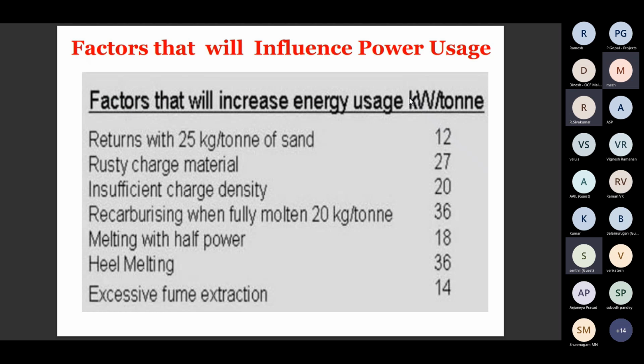So these are the various factors that will increase the energy usage in kilowatt hour per tonnage. These statistics are average statistics. Returns with 25 kg per ton of sand for 1 tonnage leads to 12 units extra. The rusty charge material may consume another 27 units. Insufficient charge density also takes 20 units per ton. Recarburizing when fully molten, 20 kg per ton, leads to 36 units.